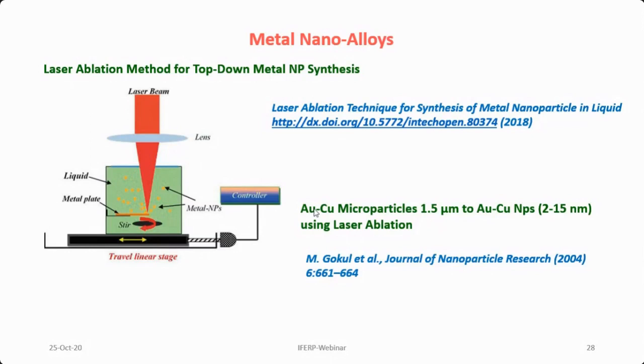So what they have done is a laser ablation technique on gold copper microparticles. The microparticles were around 1.5 micron in size, and in solution they did this laser ablation with stirring, and they could achieve gold copper nanoparticles of around 2 to 15 nanometer size. So laser ablation is basically a top down approach where you can start with a bulk material and go to nano, and this is a very good example, and this was an Indian group. They published in 2004 with this laser ablation.